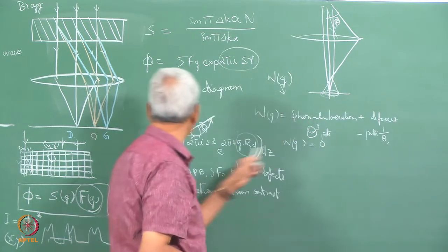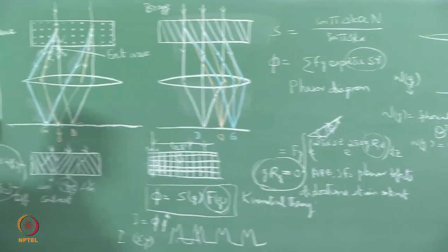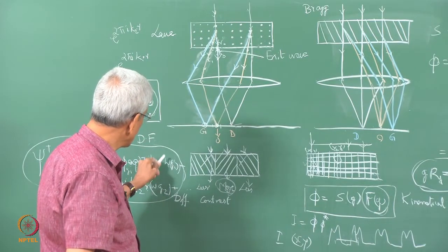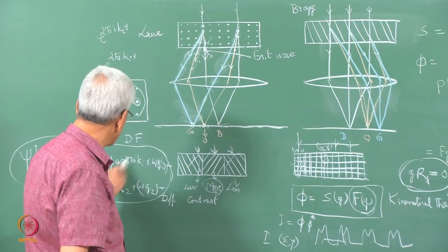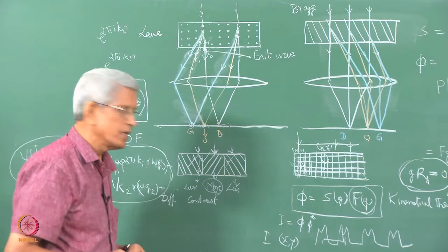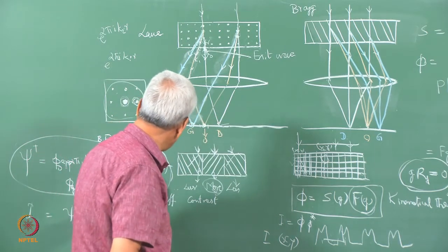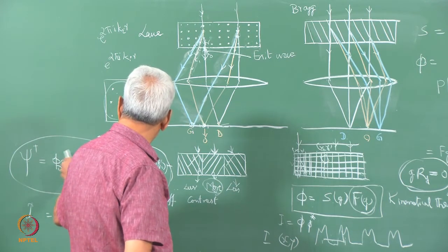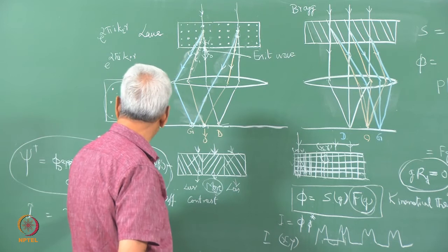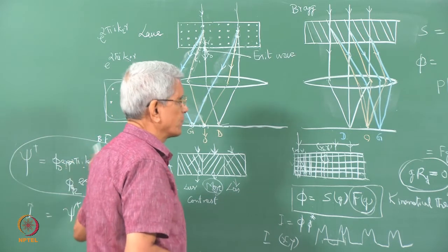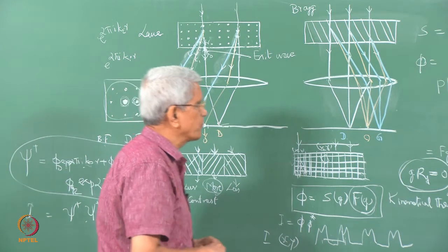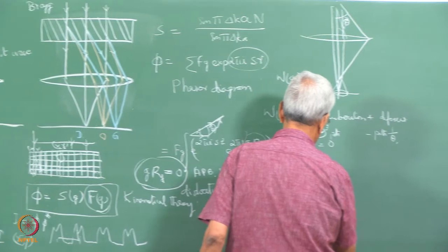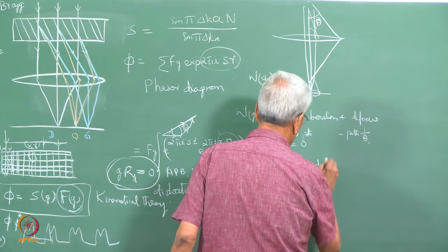But since we are using so many diffraction spots, each will have a different value. If we can optimize the condition such that for most of these reflections this value turns out to be some specific value and close to each other, so that each of the different spots adds to the contrast, adds to the amplitude, that condition is called the Scherzer defocus condition.